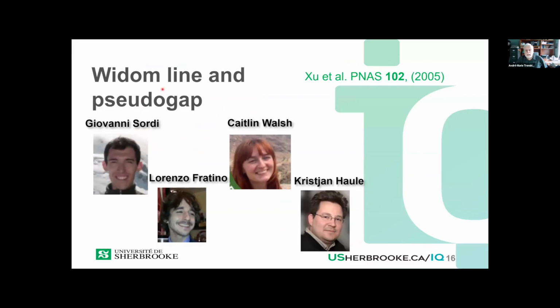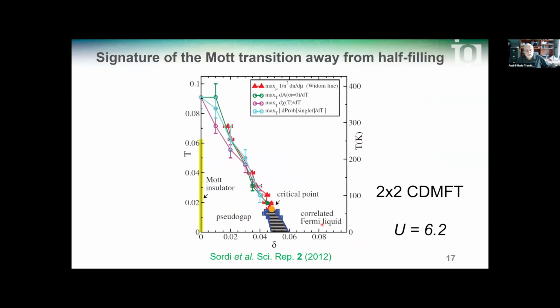Okay. The relevance of the Widom line in electronic fluids was worked out by Giovanni Sordi and his students, Caitlin and Lorenzo, in collaboration with Kristjan Haule. This is the cluster dynamical mean field theory, normal state, temperature-doping phase diagram of the one-band Hubbard model on a square lattice. It shows a first-order transition that I call the Sordi transition, separating a pseudogap phase and a correlated Fermi liquid in the ground state. There's a critical endpoint and a variety of crossovers. In particular, there's a maximum in the compressibility indicated by the upper red triangles, a prediction of this calculation. Please recall this because I will come back to that later.